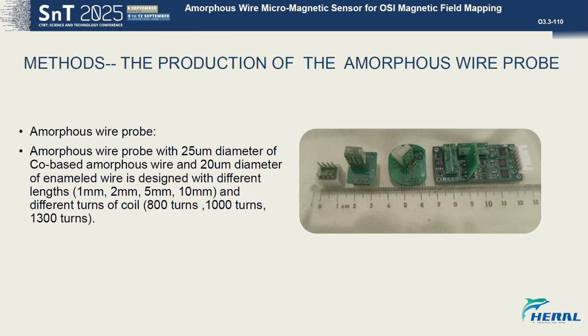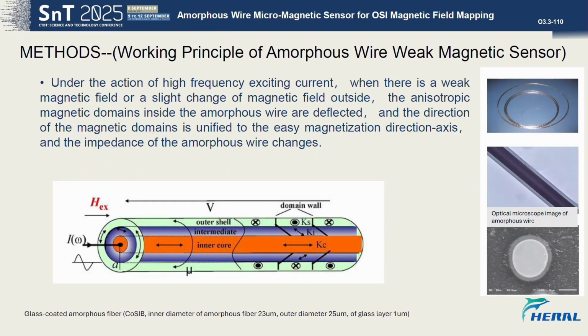They are all amorphous wire probes with different lengths and different turns of coil. Under the action of high-frequency exciting current, when there is a weak magnetic field or a slight change of magnetic field outside, the anisotropic magnetic domains inside the amorphous wire are deflected, and the direction of the magnetic domains is unified to the easy magnetization direction axis, and the impedance of the amorphous wire changes.